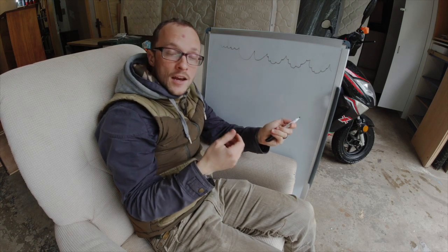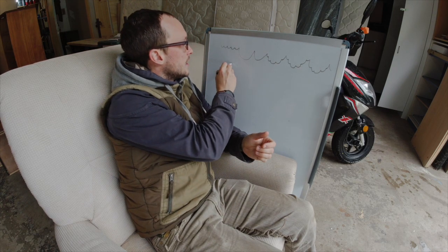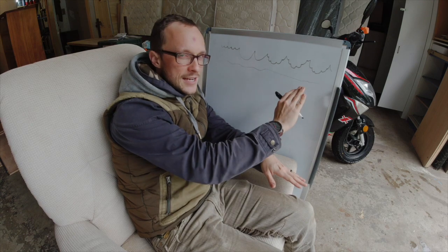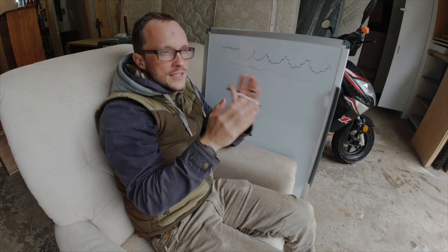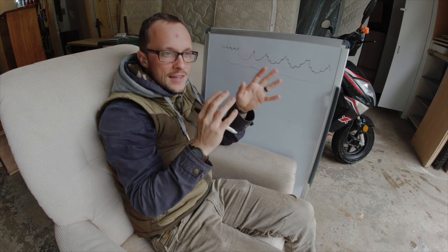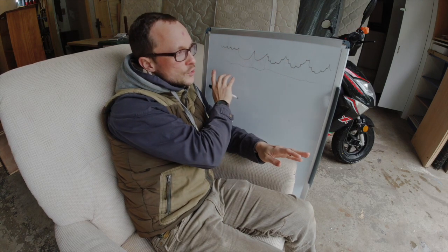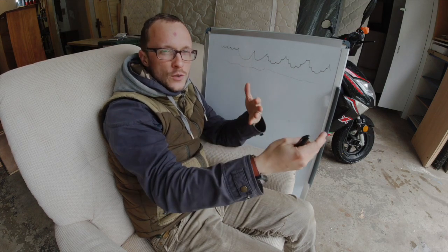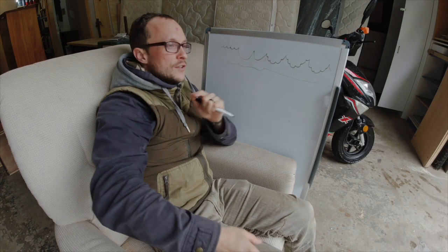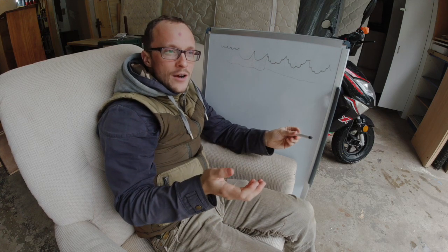Even before anything of late happened, some guys sharpened the edge that way and looked at it under a microscope, and they found that the edge was largely linear — a little bit bumpy, but largely linear. There's not a big serrating effect going on. So I reasoned that maybe these large high points of texture behind the edge are holding carbides up there, and when you wear away the fine edge it gives rise to an uneven edge which acts like a toothy edge after your fine edge is gone. That's been my theory up until now.